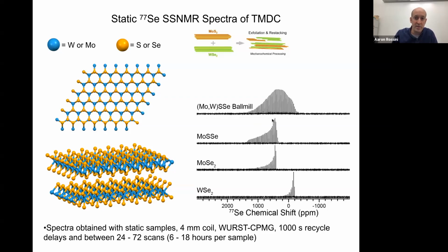When you go to the mixed materials, in addition to creating those radicals that help reduce the selenium T1, and in some cases destroy the radicals for the DNP, you're going to have a big distribution in the isotropic chemical shift. That's going to reduce the selenium peak overlap, and that's going to reduce the selenium spin diffusion rate.